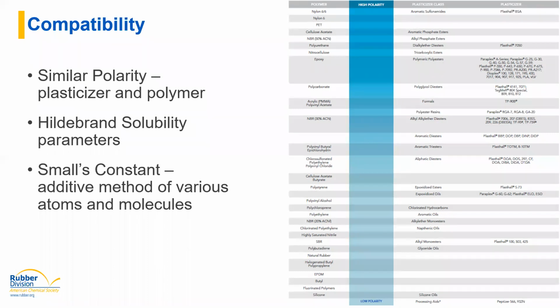Going even further, that's more of a relative, qualitative guess while we're looking at these materials. But if you want something a little bit more quantitative, you can start looking at Hildebrand solubility parameters. Those are often calculated or tested and published for a lot of common elastomers, and maybe for a plasticizer class, not necessarily a specific plasticizer unless it's a very common commodity material, but you can at least estimate using those numbers. And then going even further, you can get into Small's constants, looking at additive methods of the actual atoms and molecules that are present.